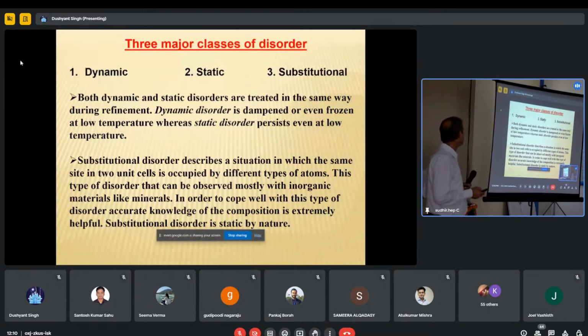If the disorder is static, even if you collect the data at low temperature, you are not able to resolve its disordered component. Both dynamic and static disorders are treated in the same way during refinement. Dynamic disorder is frozen at low temperature, whereas static disorder persists even at low temperature. By collecting data at low temperature, there is no effect on substitutional or static disorder.